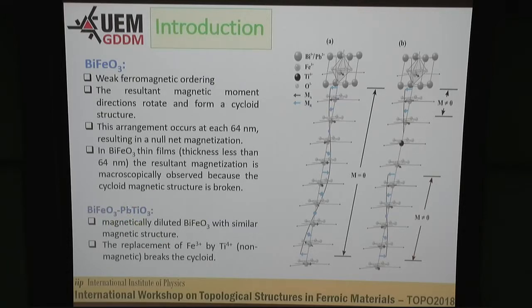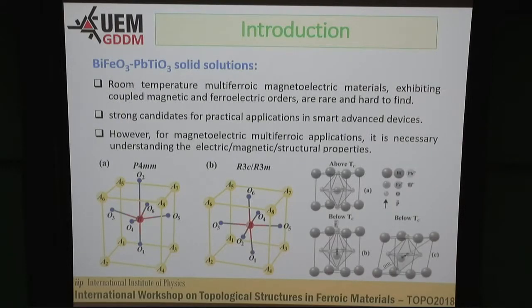by diluting lead titanate in BiFeO3. And this replacement breaks this cycloid. This is very interesting because you release the magnetization of the system. But also you can have very interesting electric and piezoelectric properties for this system. In fact, these solid solutions are multiferroic magnetoelectric materials with magnetoelectric coupling at room temperature. Strong candidates for practical applications in smart devices because some of these responses are very high in these materials in bulk form.